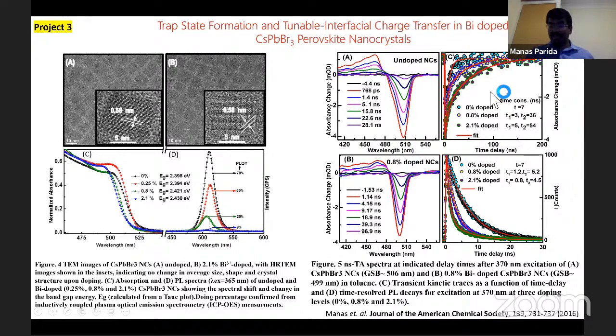Here again you can see the pump probe technique. In the undoped nanocrystal, we measure the change in optical absorption using pump probe, and see how much time is required for it to recover, like 28 nanoseconds. For the doped one, it has become slower to come back, because the complete recovery is taking like 97 nanoseconds. This shows how much time is required to recombine, and the doped one has a recovery time constant that increases.